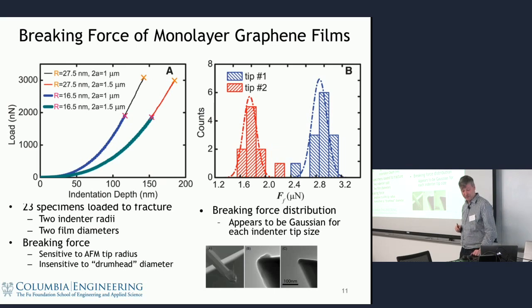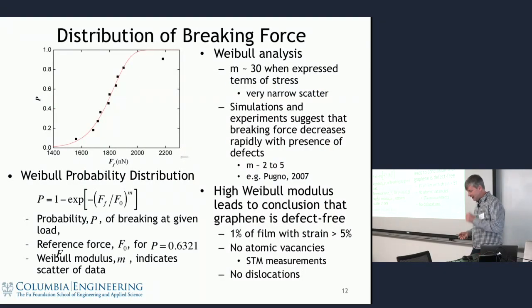In normal fracture mechanics, you expect something called a Weibull distribution, with this function here. The idea behind the Weibull distribution is that if you have a random distribution of defects in a material, you're going to get a widely varying statistical variation of breaking strength, and only a few samples will approach the maximum value, and you'll get a long tail below that. So we see more of a Gaussian distribution, which tells us that we're not seeing a statistical distribution of defects or breaking strength. We're seeing something that's intrinsic, probably with variation due to experimental issues rather than the material itself.